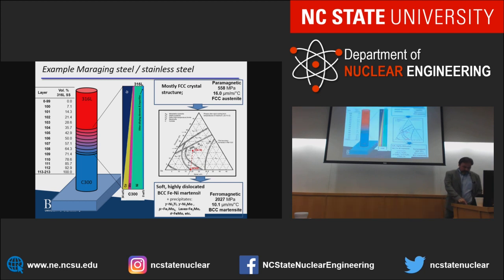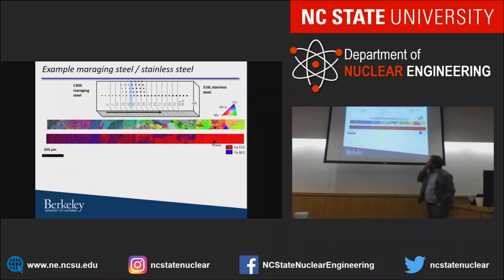And so we make these gradients and then look at them and see if they actually turn out to be gradients, if they are continuously different. So we build these structures and then do an EBSD, electron backscatter diffraction map, which tells us about phase fractions along the length. How much BCC versus how much FCC you get. BCC being the maraging steel, FCC the 316. And the blue being the BCC and the red being the FCC crystal structure. And you see that it continues, right? We've changed the composition continuously, and therefore we would expect that.